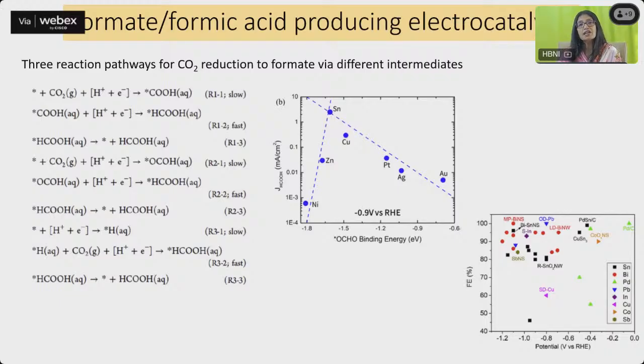So now let's see how we can generate formic acid from this carbon dioxide reduction. All these different reaction steps are given over here. You can read them at leisure. But what we are seeing over here, one of the primary steps is the binding energy. So it's the OCHO binding energy that we are having with the metal. With the formic acid, we are having this particular surface being generated, and on this surface, the metal surface has to bind. So you're looking for catalysts. Again, we are seeing the exchange current density versus the binding energy of these metals on this surface. And what we see is tin is sitting right at the top over here. So that means tin is going to be a very good material which can act as an electrocatalyst for the formation of formate and formic acid via carbon dioxide reduction.